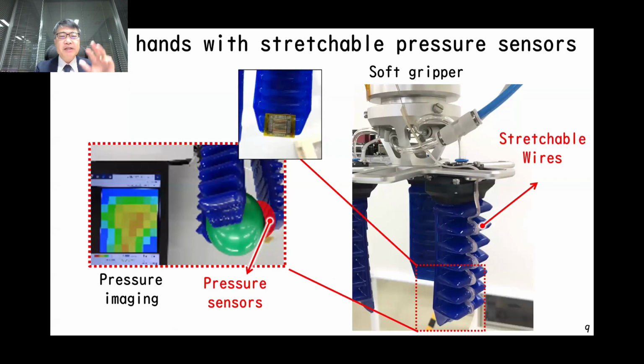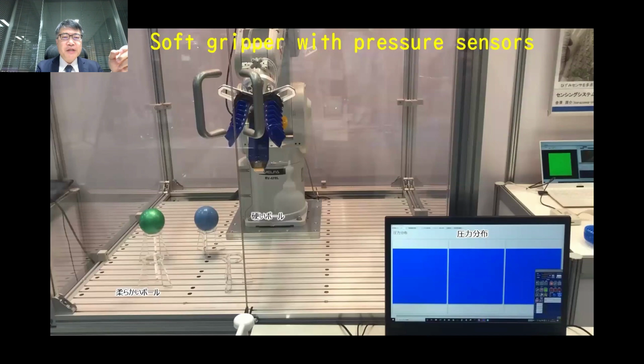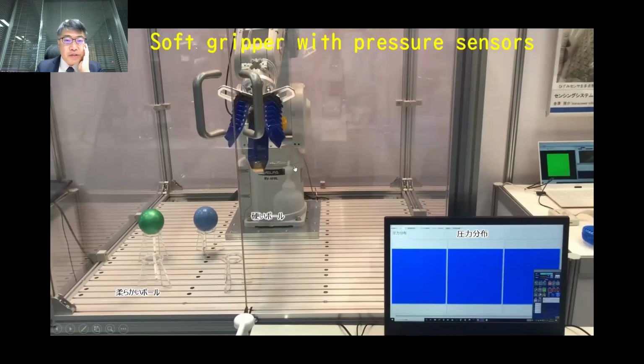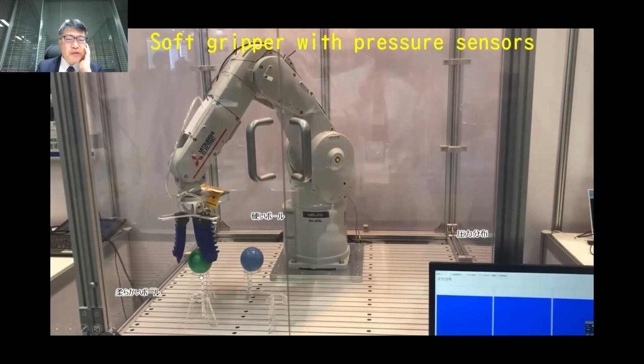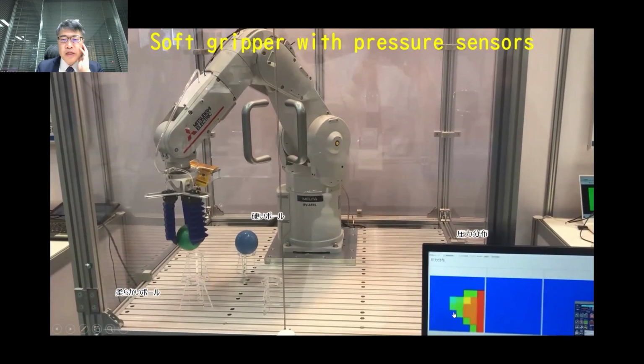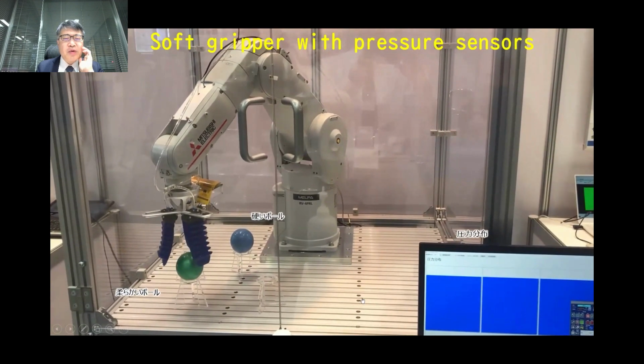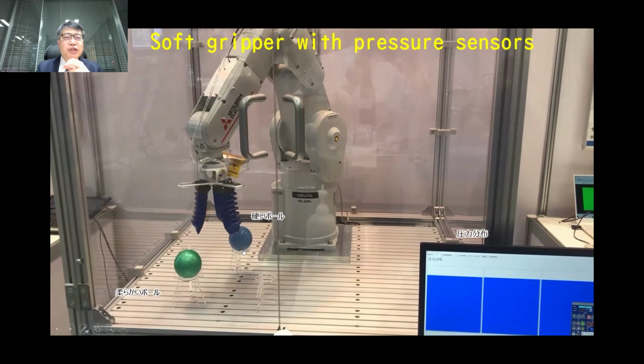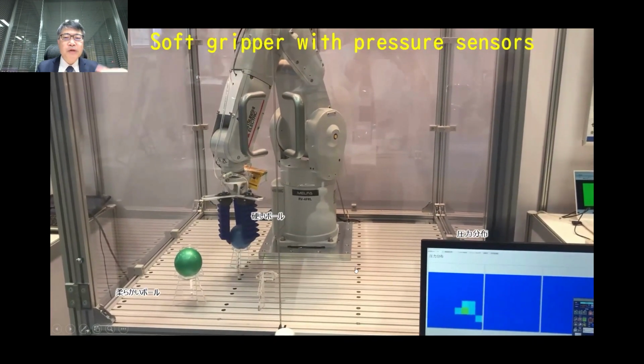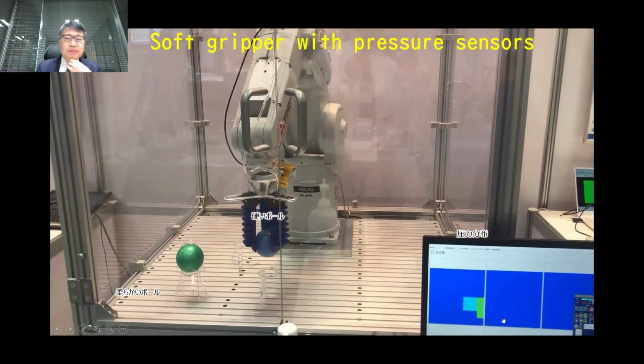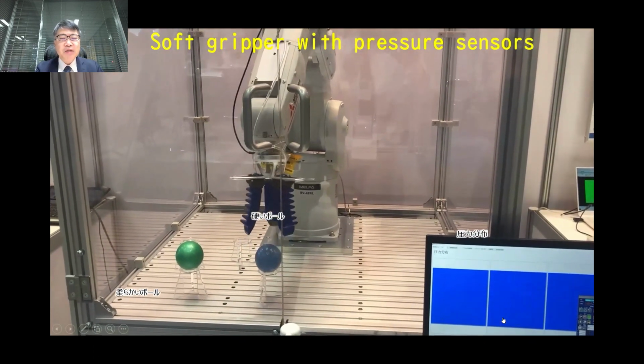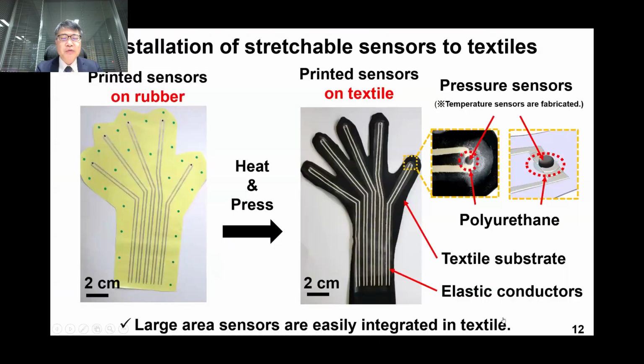So our device could be put onto a soft gripper, and on the fingertip, we can put an 8 by 8 flexible pressure sensing element. And you may see how our device works. Those two balls look similar, but when we touch the soft ball, the contacted area is very large. But the blue ball is very rigid, thereby with application of the same force, the contacted area is very small. So in that way, we can distinguish the material stiffness by using this soft gripper.